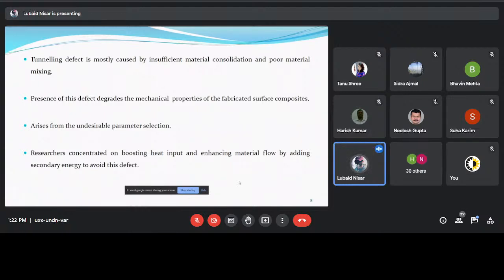As we know that the presence of this defect degrades the mechanical properties due to reduction in load carrying cross-sectional area, thus decreasing the strength of the process zone. It arises from the undesirable parameter selection. Researchers concentrated on boosting heat input and enhancing material flow by adding secondary energy to avoid this defect.